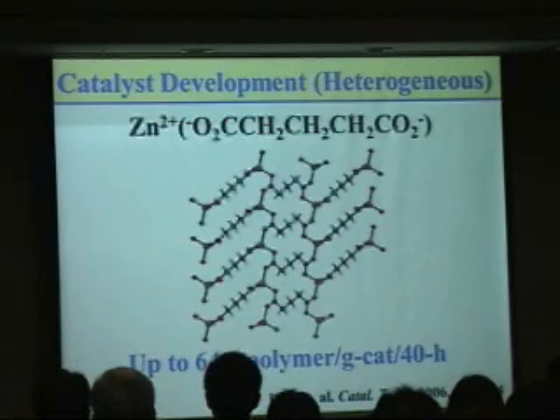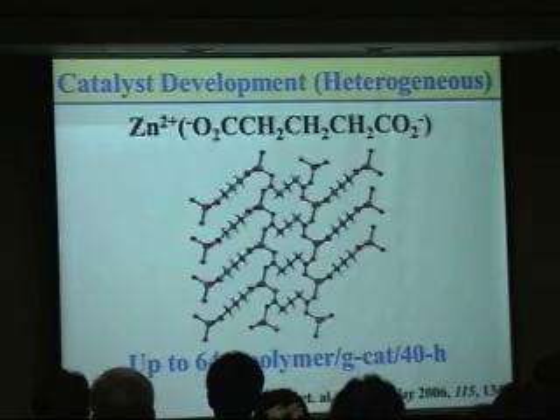The heterogeneous catalyst has been significantly improved, and the most highly active catalyst in the literature is the zinc glutarate complex. So with 1 gram of catalyst, Professor Lee, Pohang University, can make 64 grams of polymer by running 40 hours. This catalytic performance is not sufficient when we consider commercialization.